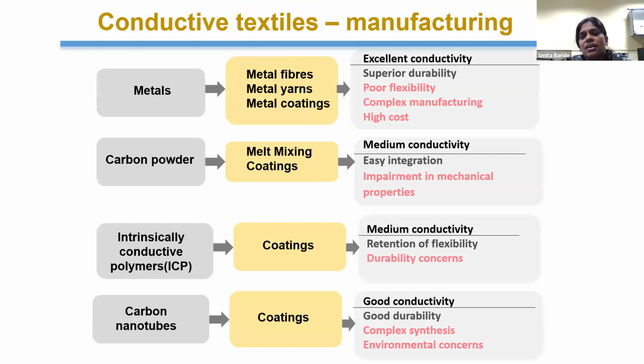Traditionally, these conductive textiles rely on metal-based technology, where metal is deposited or applied over the fiber or yarn, or directly on the fabric through coating or various methods. It gives excellent conductivity to the fabric, but due to weight burden, loses the flexibility of the fabric. Also, many times it involves a complex and costlier manufacturing process. And many times we need to import the material to make the conducting fabric. So to overcome these issues of metal-based conductive textile, there are other alternatives by which we can make a flexible conductive fabric.